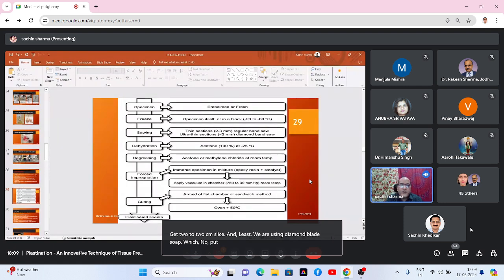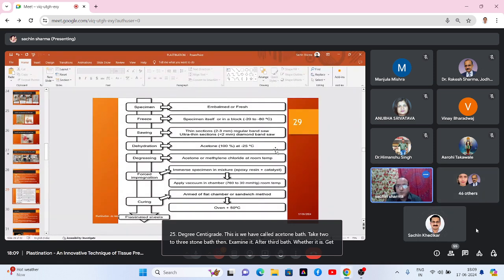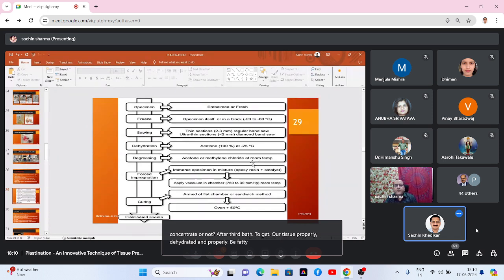So after cutting, dehydrate. In this procedure, remove the water and lipid with the help of acetone, that is 90 to 100% at -25 degrees centigrade. This is what we call the acetone bath. Take 2 to 3 acetone baths. Then examine after the third bath whether the acetone has turned yellow or whether the acetone is at 98% or 100% concentration. After the third bath, we can get our tissue properly dehydrated and properly defatted, fat-free tissue. Now, for some time at room temperature, again dip the tissue in acetone.